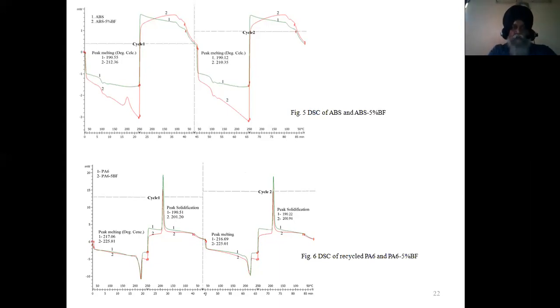So what you can see as a thermal characterization, if I make a composite wire in which the thermoplastic ABS has been reinforced with agriculture waste, which in this case is banana fiber, there is an increase in the heat capacity. Similarly, for another thermoplastic, which is polyamide, one form of nylon, polyamide 6, you can see again in the first cycle, it can manage up to 217. Then in the second again in the same range, and once there was addition of the banana fiber, its heat capacity or the maximum has increased.